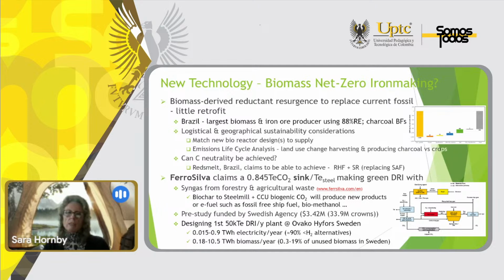Now, RedSmelt in Brazil is saying that they can achieve net zero using a rotary hearth furnace and a smelt reductor to replace this submerged arc furnace. There's a new technology called FerroSilva. They're claiming that they can actually produce a sink of 0.845 tons of CO2 per ton of steel. Then they would be making green DRI from syngas that they will get from forestry and agricultural waste. They'll put biochar to the steel mill and they will capture the CO2 and they will produce new products such as fossil-free ship fuel and biomethanol.